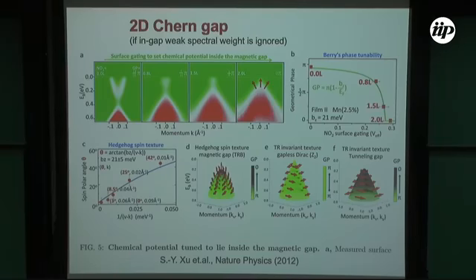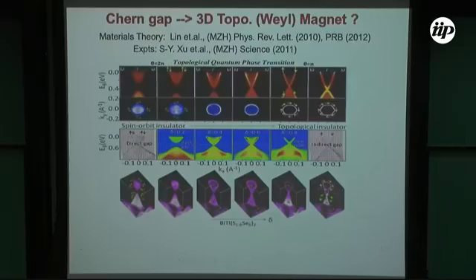So if this is a 2D topological magnetic insulator, then there should be an edge state. So now the question is, are we seeing that edge state? These experiments are done with ARPES. ARPES is not good for looking at the edge state, but it can look at the surface state. So our signature is this Berry phase tunability and the spin texture. And then later on, people have seen those edge states, both in transport and in other scanning probe measurements. We ourselves did not detect the edge state, but it's a Chern gap state.